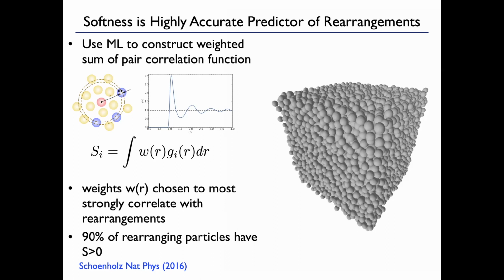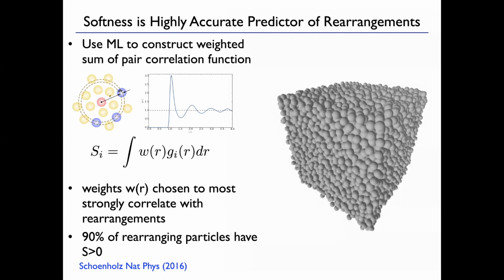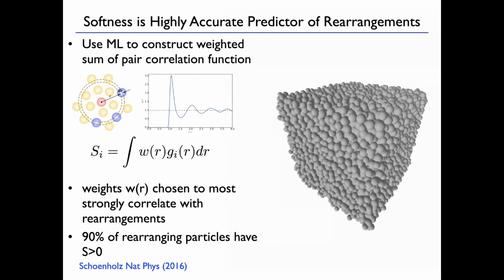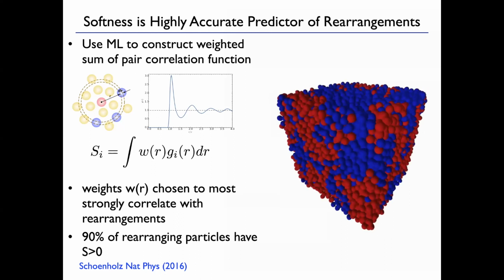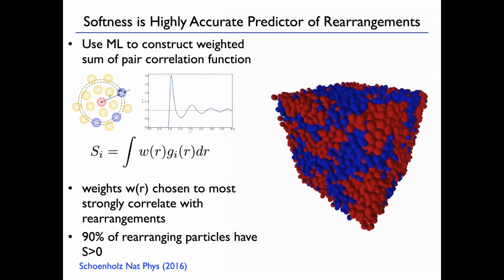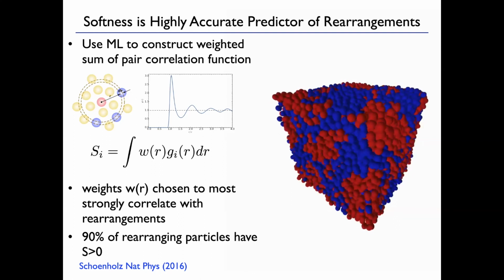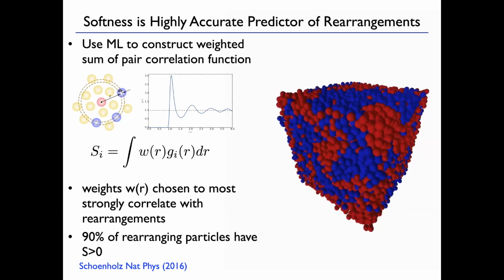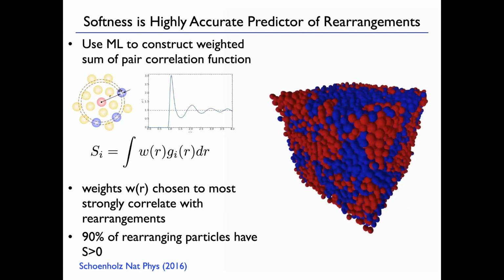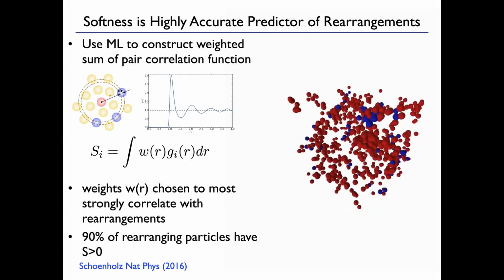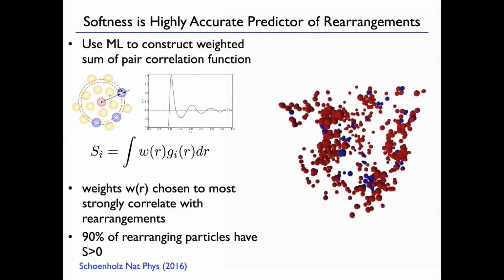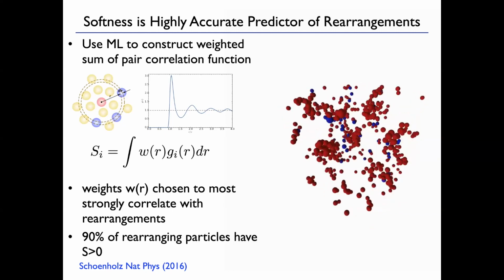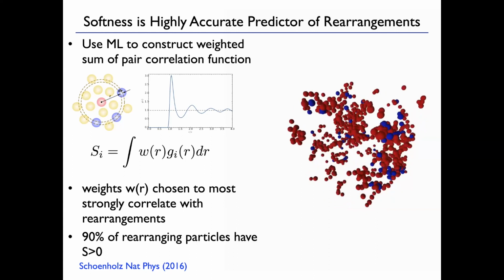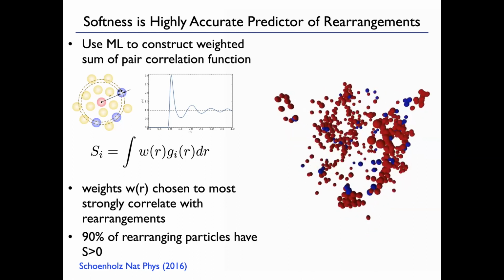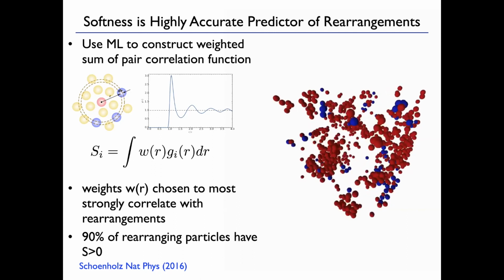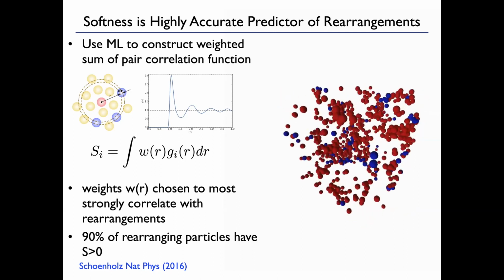Okay, so I'm going to show you this movie. This is the MD simulation of a Lennard-Jones mixture. The red particles are on the rearranging side of the hyperplane, positive softness. The blue particles have negative softness. This is above the glass transition, but not very far above it. And now it peels away to look only at the particles that are rearranging, and you see that 90% of them have positive softness, are red. So it really does work. We are very successfully able to identify which particles are likely to rearrange.